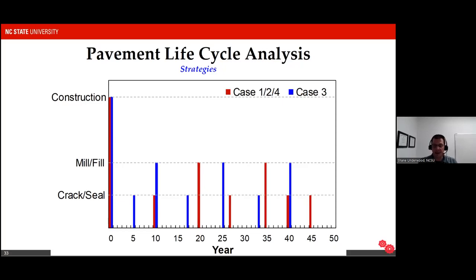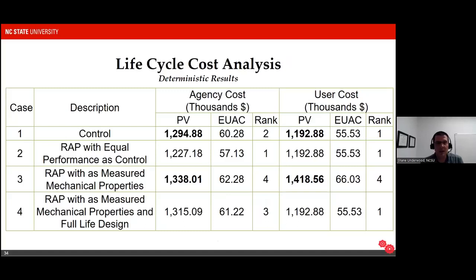Now, I'm sidestepping the details of that to get to the main conclusion, which is that when we look at the costs of using RAP, and I think the important part is that these are specific to the mixtures we evaluated, the actual net cost of using recycled materials, because they're performing worse, was actually quite a bit higher than what we saw from the control mix.